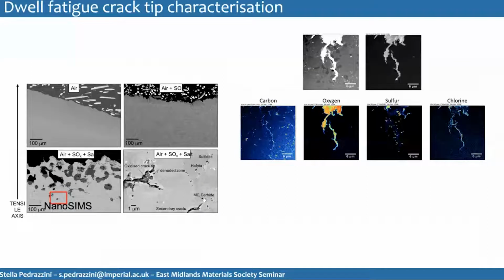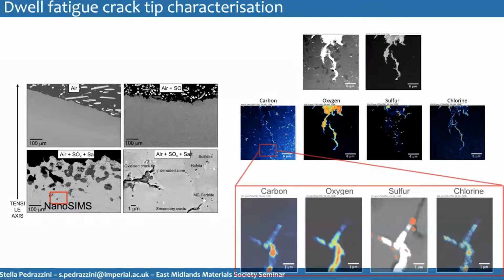So at this stage, I figured out that I needed to take a step back and look at a larger field of view in the same sort of crack here with SIMS. And in the SIMS, I figured out that actually the oxygen goes in the crack, the sulfur goes somewhat ahead and around the crack, and then the chlorine from the salt is within the crack as well. So the fact that the sulfur is primarily ahead and around the crack rather than within the crack explains why we can't detect any of that with the atom probe.